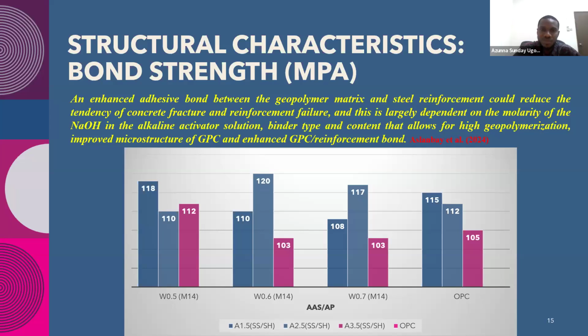So let's say you use it for a beam. The beam is going to have less deflection compared to normal concrete. Same goes for the slab. A better way to achieve a high bond strength between the concrete and the reinforcement is by increasing the molarity, using a high molarity. If you're doing a structural element design, the recommendation here is 14 molar, to enable you to have good workability, sufficient duration to cast your concrete, and also the strength that you desire.